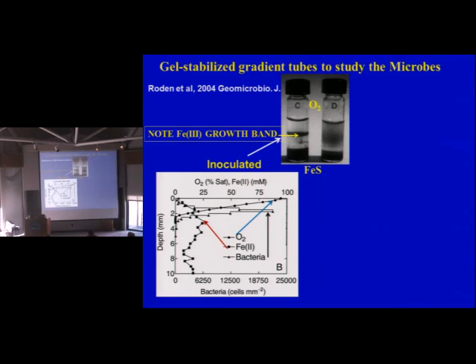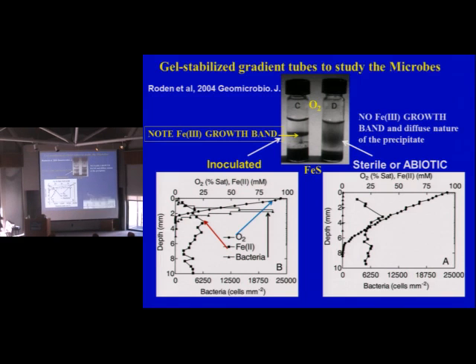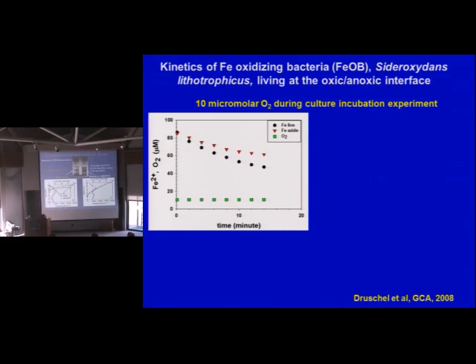All right? So if you don't put in an inoculum, you don't get a growth band. You just get indiscriminate precipitation. And that is amorphous versus the different kinds of morphologies that we do get. And so in this case, you don't really get a growth band. You don't have the bacteria concentrated in one spot. You just see oxygen and iron overlapping. Nothing special. All right? Pretty straightforward.